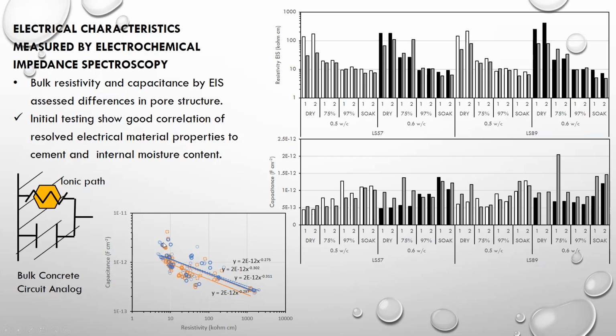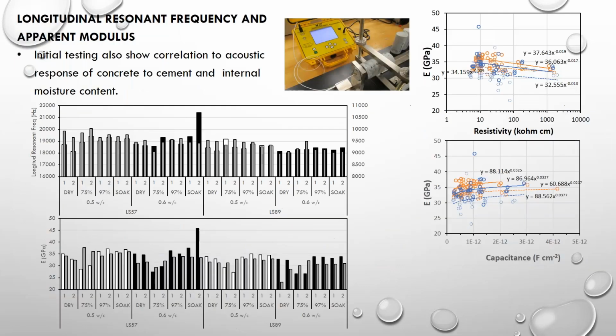So we see when we have a lower resistivity, high capacitance, we have the concretes where we have poor quality concrete with higher moisture content, and on the bottom right-hand side, greater resistivity and lower capacitance for the other concretes. So with this data, we're seeing some separation of materials, and hopefully we can get this correlation with the rapid water pressure drop samples as well.